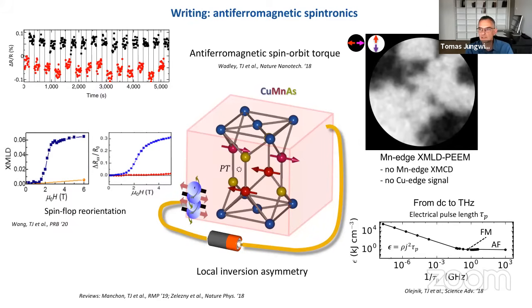So we can now electrically switch and also electrically detect the reorientation of the magnetic order. So the next very natural steps in experiments were to test whether we can scale the pulse length beyond the length that has been achieved in ferromagnets. In ferromagnets, with spin orbit torque, people managed to switch systems with pulses below 1 nanosecond. But the problem is that if you go below nanosecond, that means above gigahertz, then suddenly the energy required for switching starts to increase with decreasing the pulse